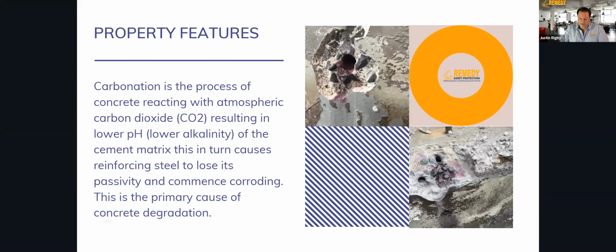Now, carbonation is the process of concrete reacting with atmospheric carbon dioxide. The concrete starts at a high pH value, which is very alkaline, and then over a period of years and decades, it slowly loses its alkalinity. The pH drops, and when it drops down towards 9, somewhere around there, the steel is not passivating itself. The steel will protect itself in highly alkaline concrete. But when we lose that alkalinity, the steel loses its passivating layer. The concrete's fine. It loves it. It's the steel that doesn't like it, and it starts corroding. And that's one of the major issues we deal with.